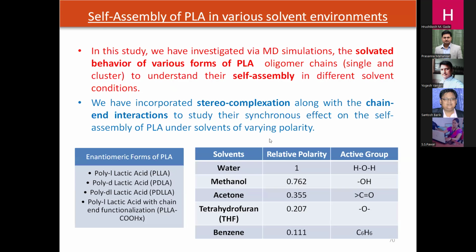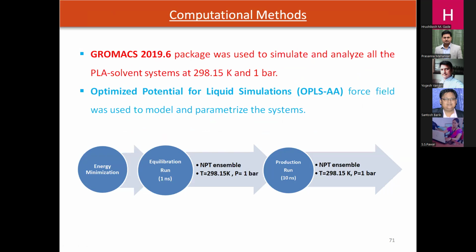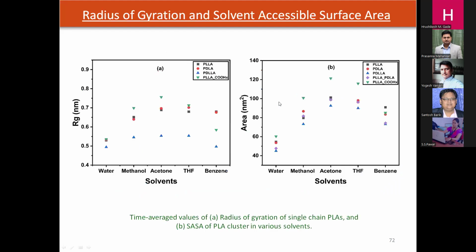Okay, so these are the combinations of solvents that we chose. In this study, we used 1 nanosecond equilibration and 10 nanosecond production. These are specific to molecular dynamics simulation, with room temperature, normal 1 bar pressure, and the force field being the OPLS-AA force field.